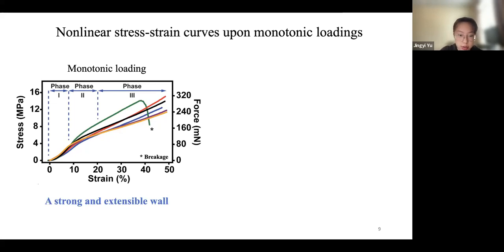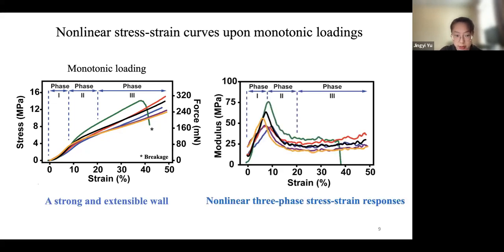And if we take a closer look at the stress-strain curve and plot the slope of the curve as a function of strain, here showing the modulus over strain, we can see that the slope of the curve is not linear. The wall stiffness actually changes at different strains, showing that overall this is a very nonlinear response, which indicates that the underlying molecular movements going on in the cell wall are different when we stretch the material to different strain levels.